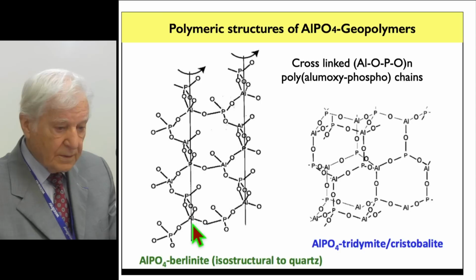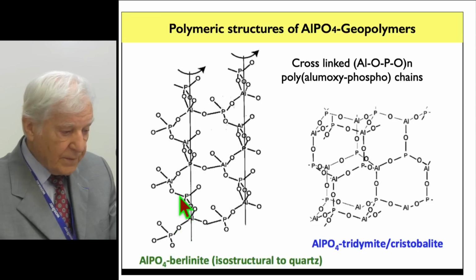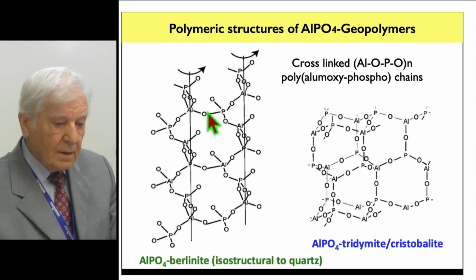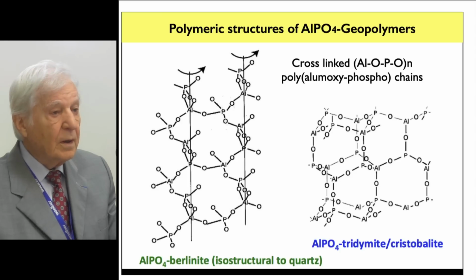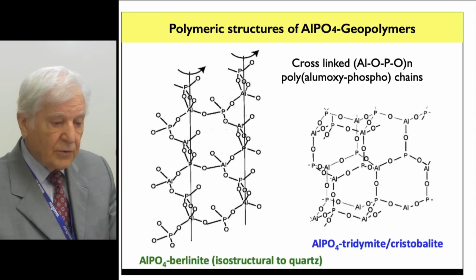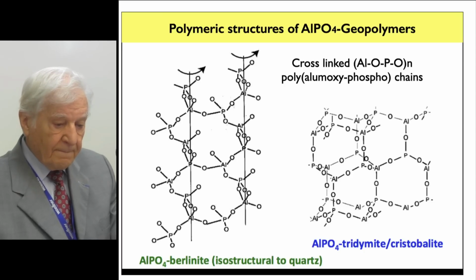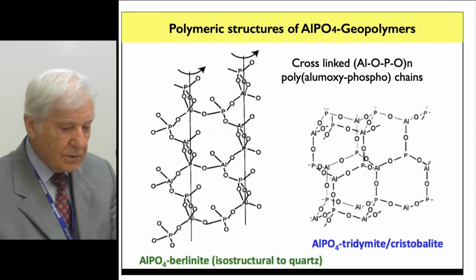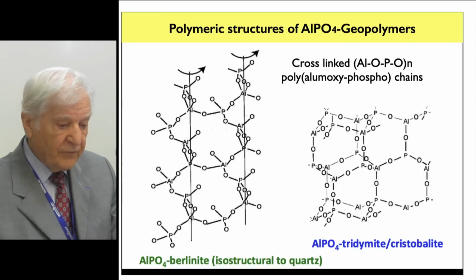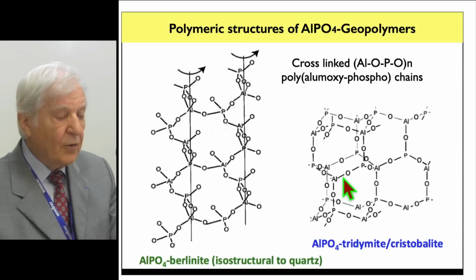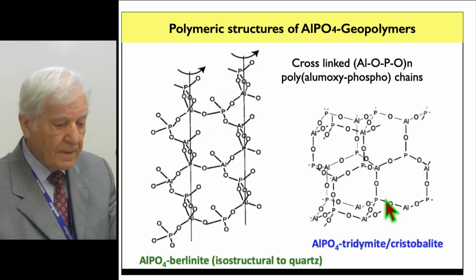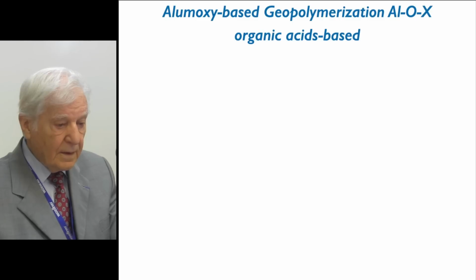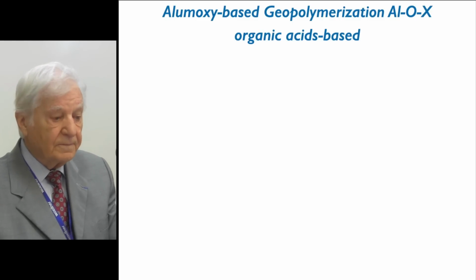It has the same structure, that is, the helical structure, which is isostructural to quartz. This explains why the X-ray diagrams of the alumoxy geopolymer aluminophosphate are identical to the X-ray diagrams of SiO2. Same for the high temperature quartz structures aluminum phosphate tridymite and aluminum phosphate cristobalite. Instead of SiO, SiO, SiO units, we have AlOP units, but they are identical. So this structure is very, very stable.